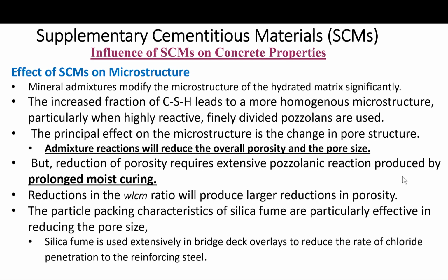The particle packing characteristics of silica fume, for example, are particularly effective in reducing pore size, and for this reason silica fume is used extensively in bridge deck overlays to reduce the rate of chloride penetration to the reinforcing steel. That's one great advantage of using silica fume.